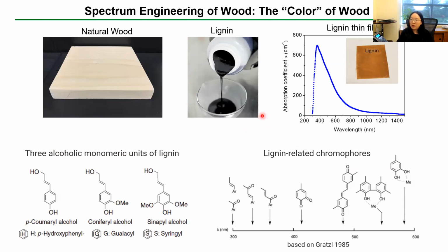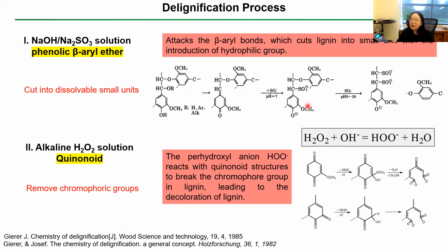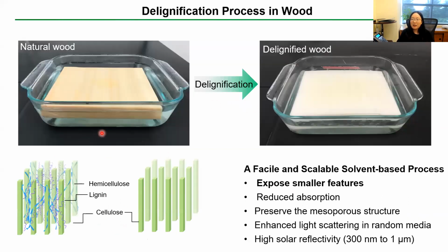We extract the lignin and do a spin coating, and you will see that the absorption peaks lie within the visible range. We use a chemical-based treatment, and it's worthwhile to know that these chemicals are commonly used in the papermaking industry to strip away lignin, the colored part. This is what a natural piece of wood looks like. After the chemical treatment, it becomes white.